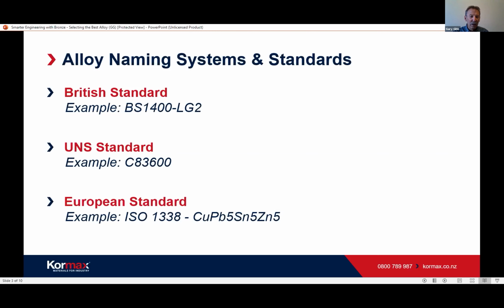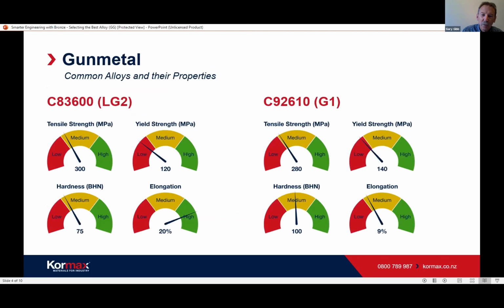So I'll now go through the individual groups. And the first one we're going to look at is gunmetal. It was called gunmetal because the cannon in the first view there was made out of this type of alloy. It's basically 85% copper, 5 tin, 5 lead, 5 zinc. It's a sort of medium duty material. It has lower tensile strength, around 300 average yield strength, and the hardness is 75 Brinell. And good elongation. So it's a general purpose material for things that are not under too much stress.